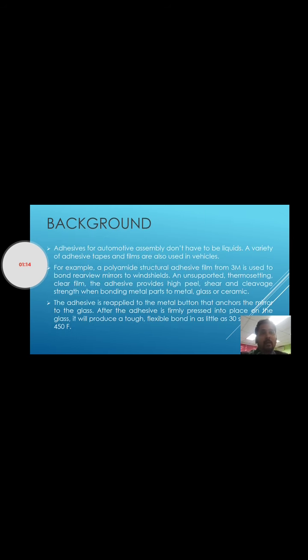This is my project background. Adhesive for automotive assembly doesn't have to be liquid. A variety of adhesive tapes and films are also used in vehicles. For example, a polyamide structural adhesive film from 3M is used to bond rear-view mirrors to windshields. It is an unsupported thermosetting clear film, and the adhesive provides high peel, shear and cleavage strength when bonding metal parts to metal, glass or ceramic. The adhesive is pre-applied to the metal button that anchors the mirror to the glass. After the adhesive is firmly pressed into place on the glass, it will produce a tough, flexible bond in as little as 30 seconds at 450 Fahrenheit.